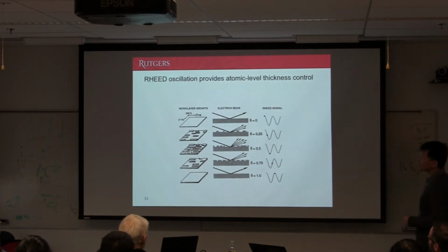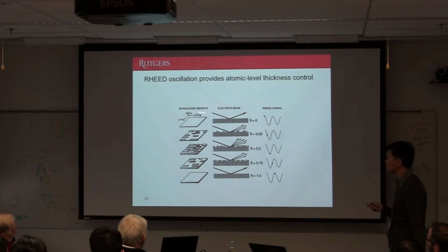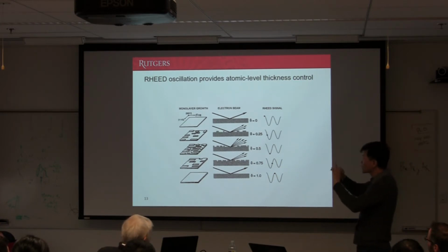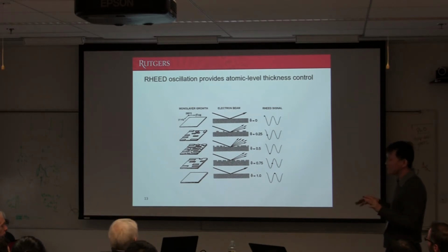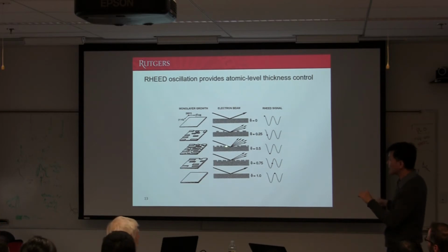One of the very frequent applications of RHEED is the RHEED oscillation. What RHEED oscillation means is that if you monitor the intensity of the beam, there's an oscillation. Usually the oscillation is correlated with atomic scale smoothness. So if you have just one atomic unit cell, say gallium arsenide, which Lauren will probably talk about afterwards, but almost any material, the minimum building block, this molecular layer, has a period that matches the period of this oscillation because of how it grows.